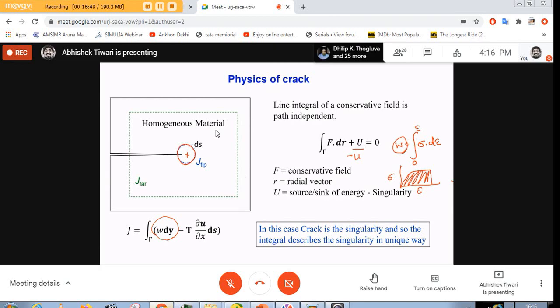And the second term, T is the traction vector, del u by del x is the displacement gradient, ds is the small element on this contour, and it tells how much amount of energy you are giving to the system. The amount of energy you are giving is stored by the material, and if there is nothing left, then this integration value will be 0. But if you have a source or sink of energy, as I said, then it will not be 0. And in this case, the singularity is the crack tip. So we have one singularity in the loop, in the contour where we are taking this integral. So we can uniquely define this singularity using this integration.